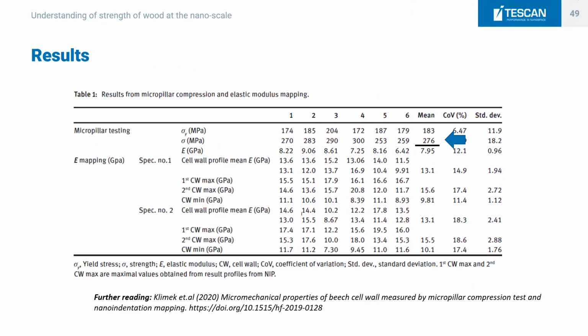And what we did was that we specified all the regular properties, so strength, modulus of elasticity, and we also matched that with a mapping from the nanoindenter and saw what the difference was. But if you would want to be very general, you could say, well, the ultimate strength of the cell wall is 276 megapascals plus minus 18. And that's not given by the nanoindentation, but really something which almost replicates regular compression experiments.